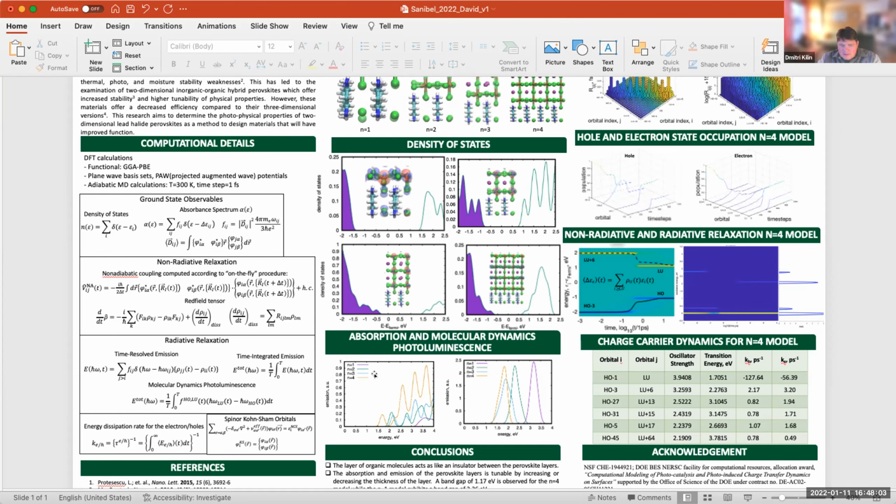Now, the corrections to optical properties. If we are looking not at absorption, but at emission, the spectra would be much more sensitive to material changes upon photoexcitation. One can identify at least three factors that would play a role for emission of a material.